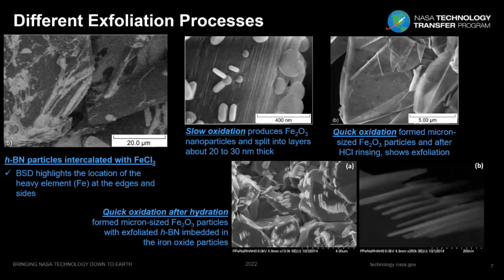nanometers thickness. But if you take that sample and then do a fast oxidation, this means that we put the sample in a preheated oven that is already at the desired temperature, the iron oxide particles develop in the micron size, and the layers of the boron nitride are a lot more separated. Here in the micrograph, in the top right, you can see that the sample after cleaning with hydrochloric acid has some layers separated from the bulk, and they are bent and a little bit transparent, and that's exactly what you are expecting to see with samples that have been exfoliated. A little bit of transparency on the layers.